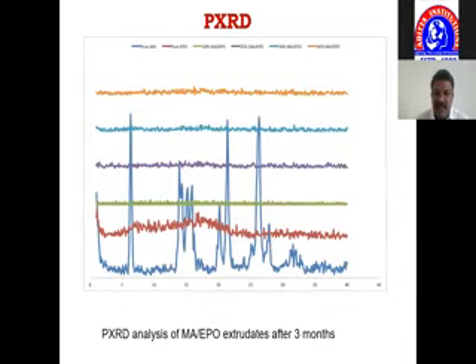The other way of understanding whether the drug has converted to an amorphous form is by the XRD method. At the bottom, what you see is pure mefenamic acid, the blue color, with lots of multiple peaks. The other peaks are of a solid dispersion made by a hot melt extrusion process. Now you can confirm there are no peaks of the drug. Hence, we assume and conclude that the drug has been converted into an amorphous form.